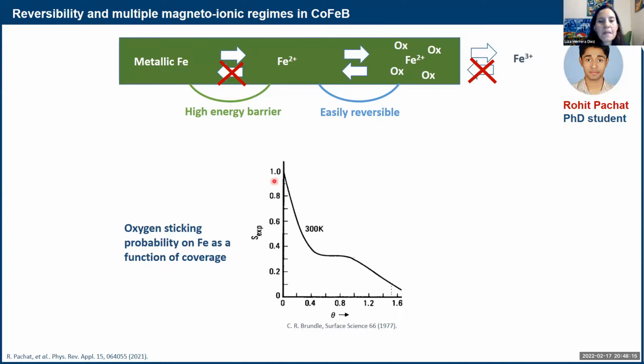So there have been studies on how the oxygen sticks to an iron surface as a function of how much oxygen you put, of the coverage that you have on the surface. They could see that when you barely have anything, the sticking probability is really high. Then as you start adding more and more, there's a drastic decrease of the sticking probability, which probably corresponds to this first phase of, as I said before, adding oxygen when there's nothing around. So it just captures the oxygen really, really fast.